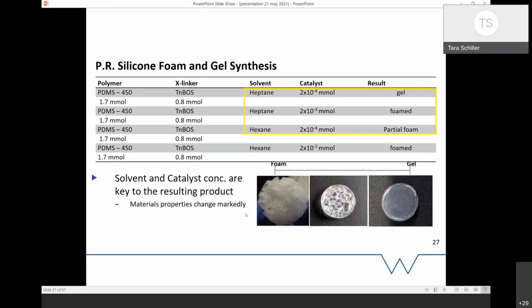And then what we noticed when we played around, you can see here with our catalyst sort of constant, we played around with the monomer. Sorry, try that again. We played around with the solvent here. The hexane formed this partial foam, which is what we can see here. The heptane with the lower concentration of catalyst foamed, and then when we use the heptane with a higher concentration, you can see here this nice transparent gel out of it, and this was kind of tunable as to how much you could get as to the changeover with it. I mean, these are obviously just 3 images, but at least it details what we were doing with this.